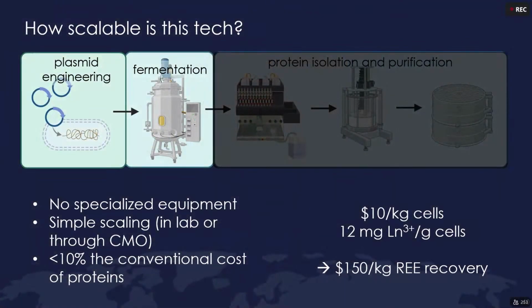We can recover about 12 milligrams of lanthanide, one of the rare earth elements, per gram of cells. And so when you do the dimensional analysis, what that means is it costs us about $150 a kilogram of rare earths to recover them. Currently, the market value for these rare earths is around $2,000 a kilogram. So I would argue at that price point, it would be worth it for companies to actually start recycling these materials, which is our goal.